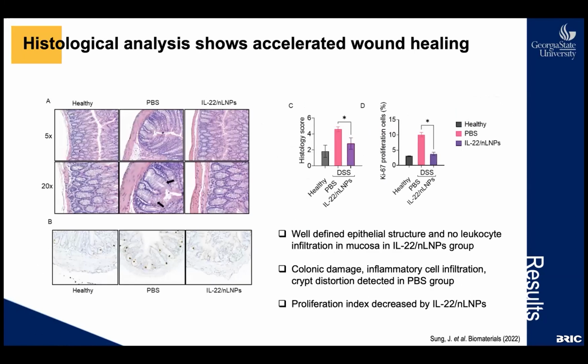Next, it's a histological analysis. I also showed that the IL-22 lipid nanoparticle accelerated the healing process in damaged intestinal mucosa. The top left image shows the H&E staining tissues. As we can see here, the IL-22 lipid nanoparticles and the healthy groups display well-defined epithelial structures and no leukocyte infiltration in mucosa, whereas the PBS treated group showed severe colonic damage like inflammatory cell infiltration and crypt distortions.